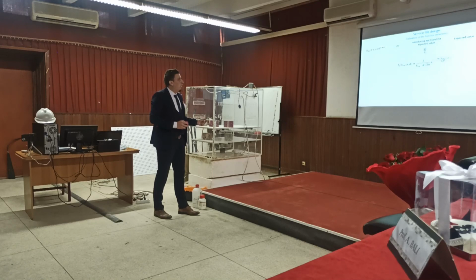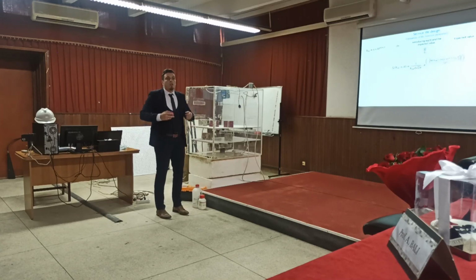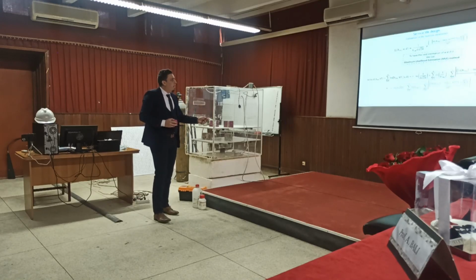Now, introducing the expected value and the relationship from the accelerated carbonation and air permeability into equation 6, we obtain equation 7, as you see here. You see here that we have two parameters, the D and the A. And in order to estimate them, we use the maximum likelihood estimation method. After several mathematical steps, we get here, written in blue, the log maximum likelihood function.